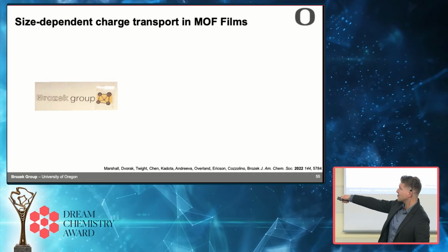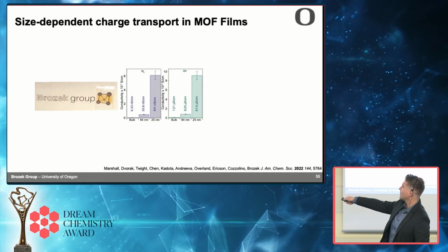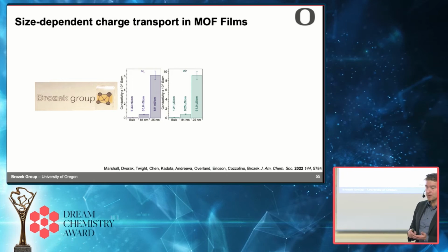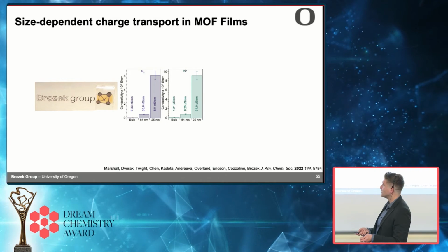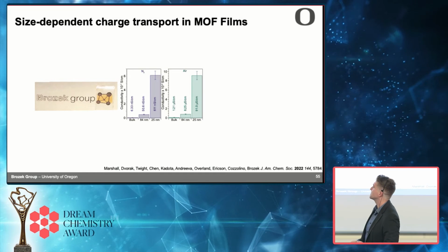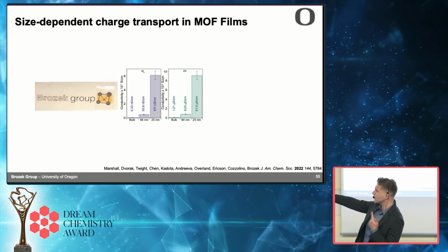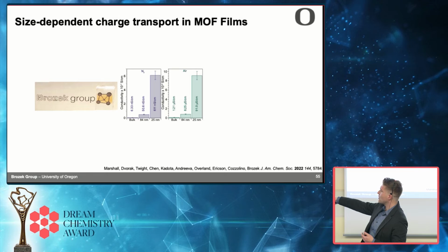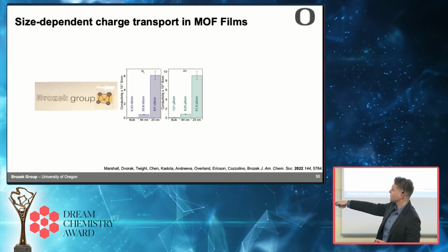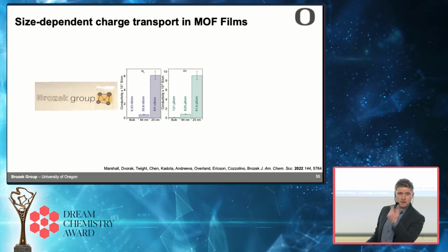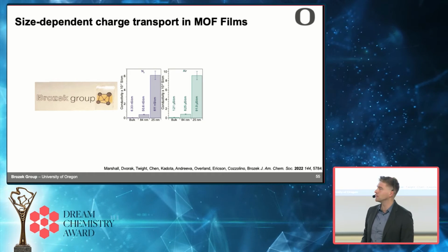Because these are so small, we can make them as thin films, like I was showing you. And now that we can make them as thin films, we can measure their conductivity using 4-point probe contact techniques, which is much easier when you can work with thin films. And whether you're working under nitrogen or in air, we see that the conductivity really increases by simply making the particles smaller. The conductivities overall are higher in air because you need to oxidize some of those iron sites. But what we see is that when you go from the biggest particles to the smallest particles, the conductivity increases by about 2 orders of magnitude. And that was unexpected for us.